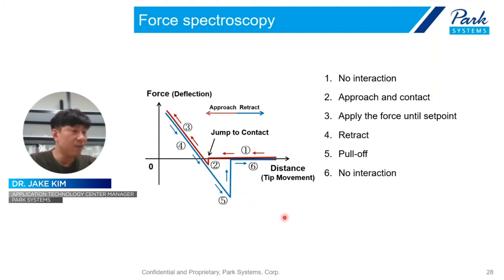This is one cycle of the FD curve. Start from number one, when the AFM tip and sample are quite far away, there is no interaction. But when the AFM tip gets close to the sample surface and contacts, that is number two, and applies force until some specific value, which we can call the set point, like this, and reaches this value, then retracts, number four. At this point, number five, pull off, the AFM tip and sample detach. And number six is the return to the initial stage, no interaction. This is just one cycle of the force distance curve.